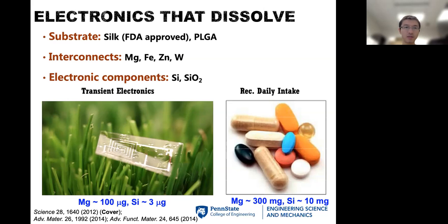And the challenge really comes from the electronic components in terms of the semiconducting materials. Silicon is the backbone of the DNA of modern electronics, but luckily, not every single material we use is this harmful, and silicon is biodegradable. It can safely dissolve in the biofluids at a very small rate, about 1 or 2 nanometers per day. But if you design everything to be a small thickness, it can be managed.